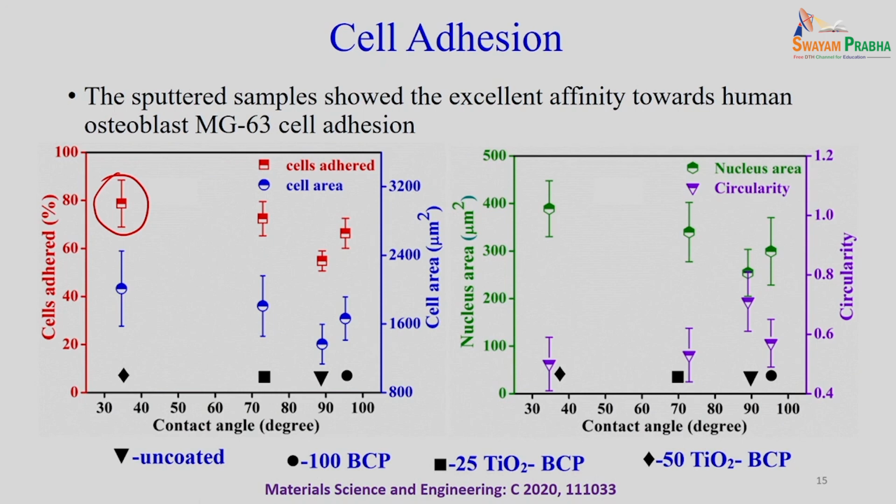So, we discussed coating using RF sputtering. In the RF sputtering, when we coated the HA, it ended up with BCP. It means it has both HA phase and TCP phase.